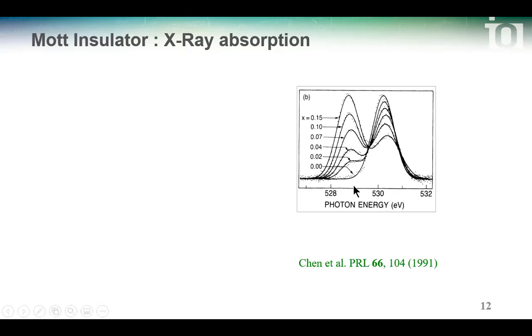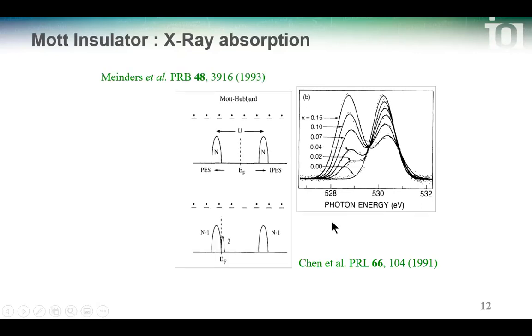So how do we see this experimentally? Like Patrick explained to me at some time, you take a very high energy photon that extracts an electron from a core state, and you look at the cross section. You see the energy here is 530 electron volts, so it's huge. And you start to be able to extract this core electron. So that's this first peak here.